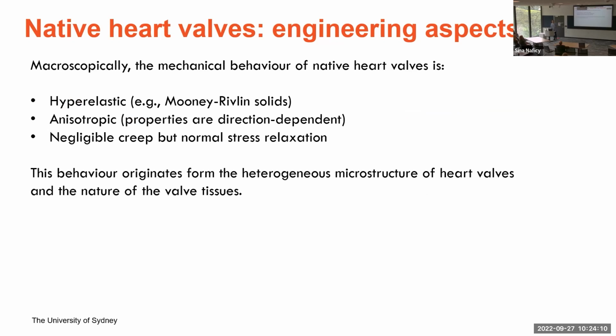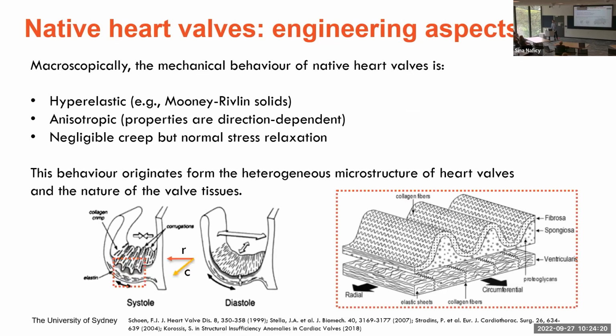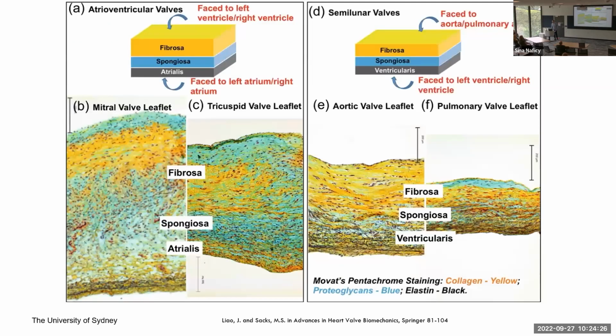The reason for such a complex mechanical behavior is that leaflets and heart valves are heterogeneous at their core. If you look at leaflets, for instance, we know that they are made of different layers. Depending on the position of these layers, we would see that not only do they have different compositions, but also any collagen fibers are aligned in a certain direction.